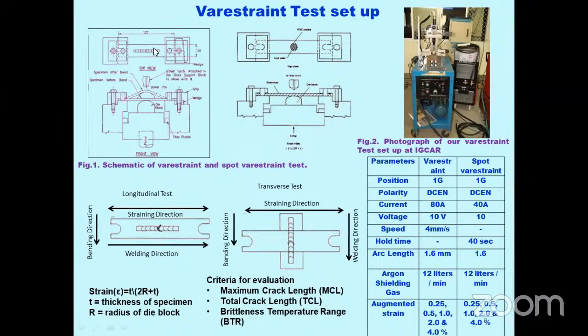So this is the Varestraint setup. Here it is an autogenous TIG torch, and we keep our specimens over an anvil, and there is a die block underneath the specimen. When this automated autogenous TIG welding is carried out over the specimen, as the TIG torch comes to the center of the specimen, the die block is activated using a ramp to bend the specimen during the weld solidification. In this way, we are externally imposing restraint on the solidifying weld pool, and we evaluate the hot cracking susceptibility of the material.